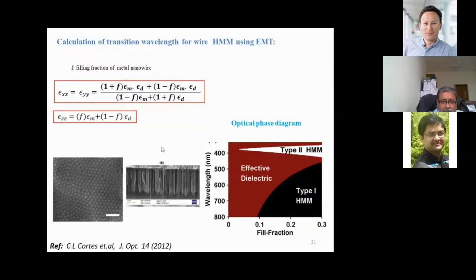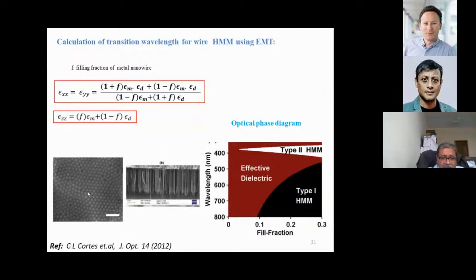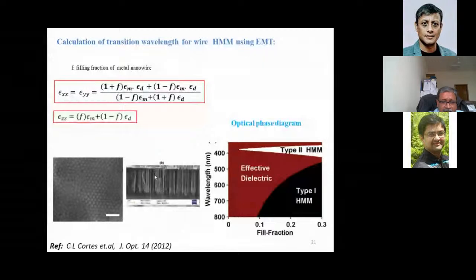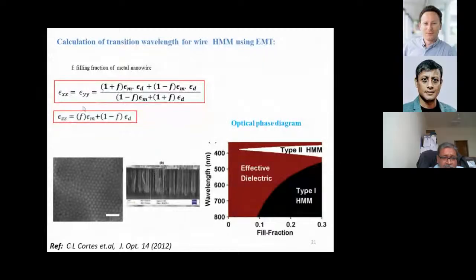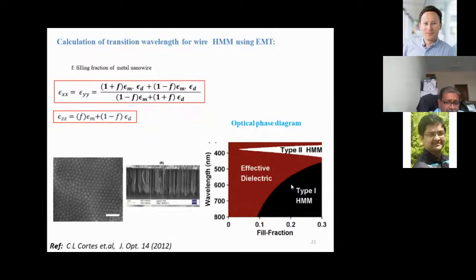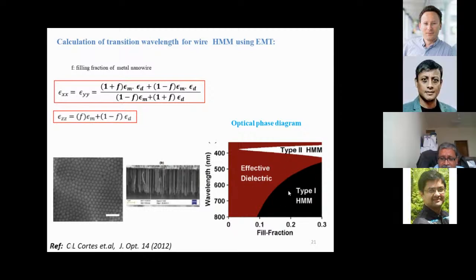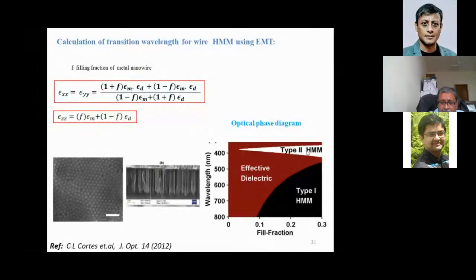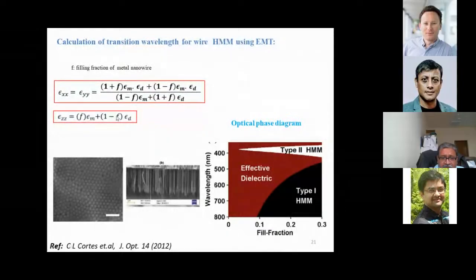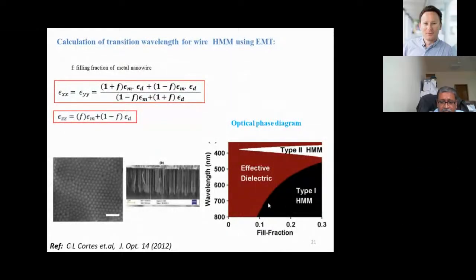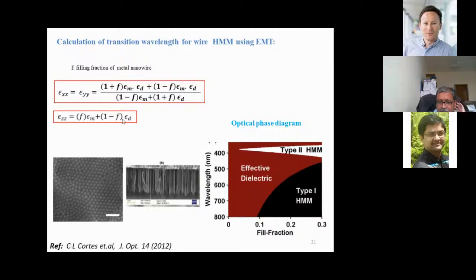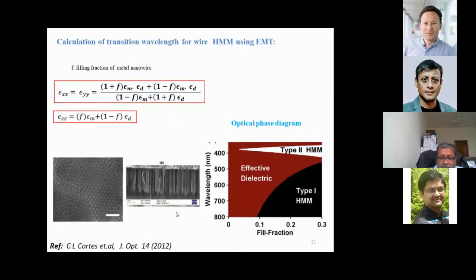They are grown in an alumina matrix, and by varying the fraction of this metal in the background, you can control the permittivity both in the plane as well as perpendicular, and accordingly you can land up in one of these regimes. What is interesting is either you are here somewhere, or you can be somewhere here, depending on how you vary the fill fraction. The fill fraction is given here. So by simply tuning this, you are able to control the dispersion property of this material.